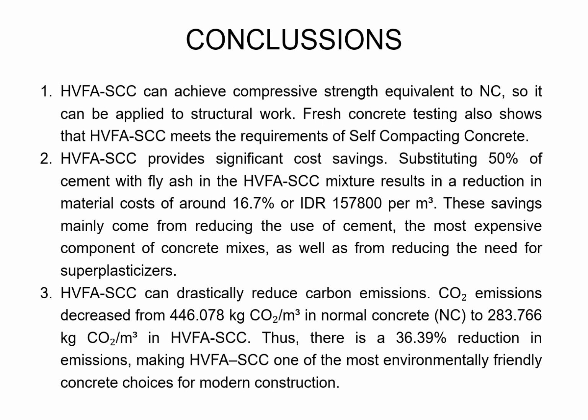Substituting 50% of cement with fly ash in the HVFA-SCC mixture results in a reduction in material costs of around 16.7%, or IDR 157,800 per cubic meter. These savings mainly come from reducing the use of cement, the most expensive component of concrete mixes, as well as from reducing the need for superplasticizers. 3. HVFA-SCC can drastically reduce carbon emissions. There is a 36.39% reduction in emissions, making HVFA-SCC one of the most environmentally friendly concrete choices for modern construction.